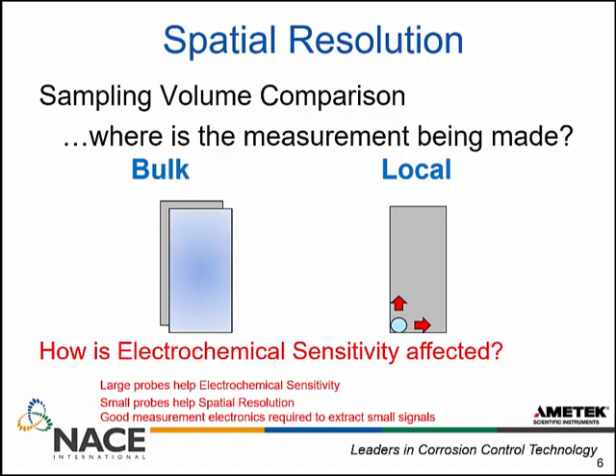Think about how electrochemical sensitivity is affected. If I have a very large probe, I get better electrochemical sensitivity because there's a larger signal to measure. But as the probe becomes smaller and smaller, electrochemical sensitivity goes down while spatial resolution improves. We see this trade-off between electrochemical sensitivity and spatial resolution. The key is that with good measurement techniques, best practices, and measurement electronics, we can extract small signals from the background — allowing us to achieve small spatial resolution while still measuring small signals.